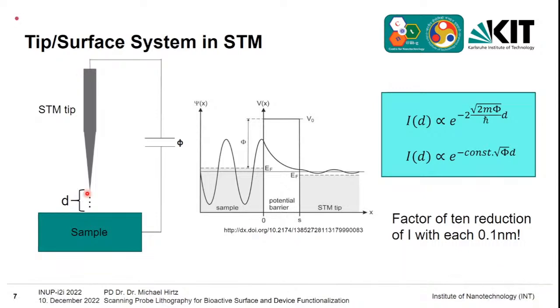So there is a sharp tip brought near to a sample, and it's not touching the sample. But if you apply voltage, we still have our gap that can be tunneled through, and then some electrons can tunnel from the sample to the STM tip. And the trick is that the amount of tunneling, because you have an exponential decay here, is very highly dependent on the distance. So you see here the current goes exponentially with the distance, and all the rest can be seen as a constant. So it's all dependent on the distance, which means you can very nicely monitor the distance between tip and surface. You have a factor of 10 reduction in the current for each 0.1 nanometer, so that's really like an atom thickness difference.